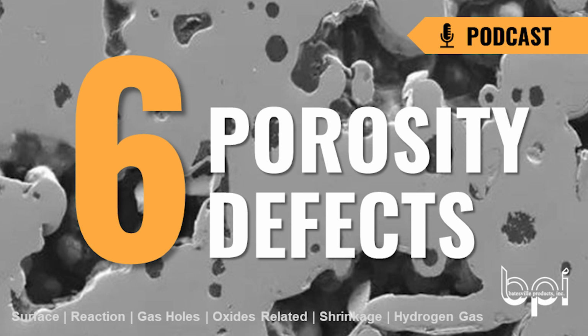Gas holes are almost always internal, almost always round in appearance. And usually they're very localized. They're usually based on metal turbulence, either something coming down the downsprue or something leaking in at some point in the gating system. They're almost always related to some form of metal turbulence. Depending on how fast the tilt pour is operating, it may hit bottom and cause turbulence in the bottom end before it goes into the casting.